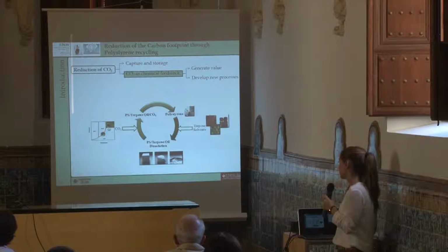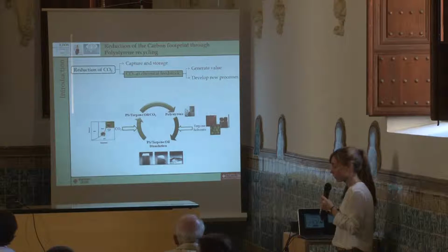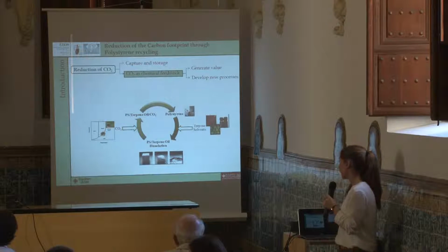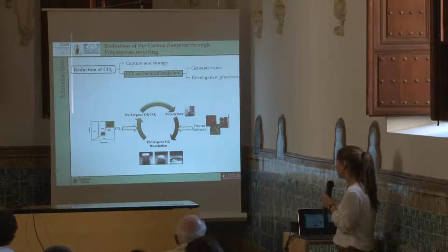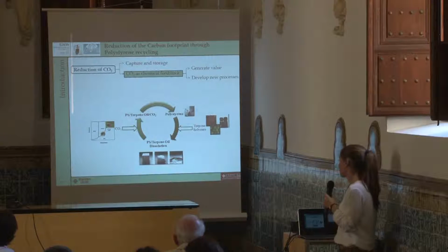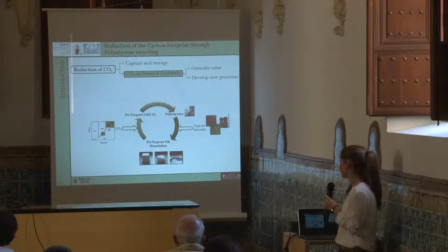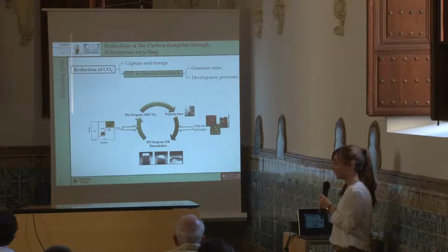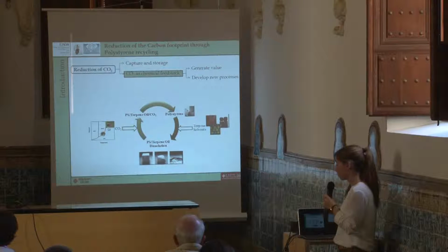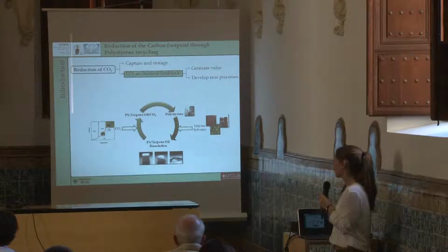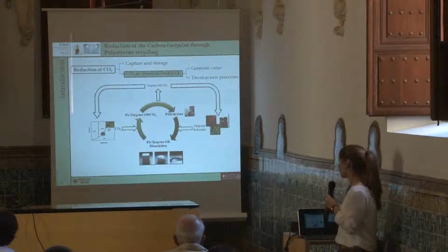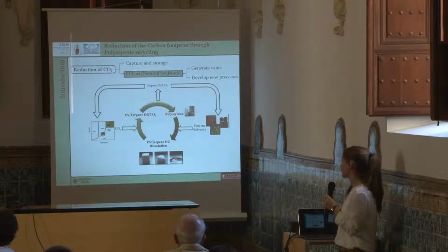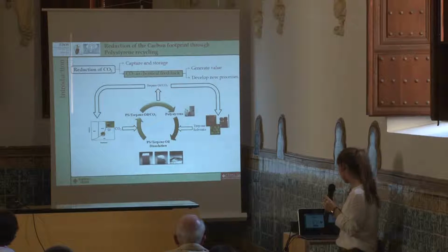Next, the polymer can be recovered using CO2, since terpene solvents are highly soluble in CO2, but polymers are totally insoluble, so they can be obtained again. Also, it's important to stand out that CO2 is inert, non-flammable, and non-toxic. It's environmentally accepted, since we are using it as a chemical raw material, and it's available at relatively low cost. Furthermore, we propose the possibility of recovering the terpene oil and the carbon dioxide, depending on the economic benefit of the global process.